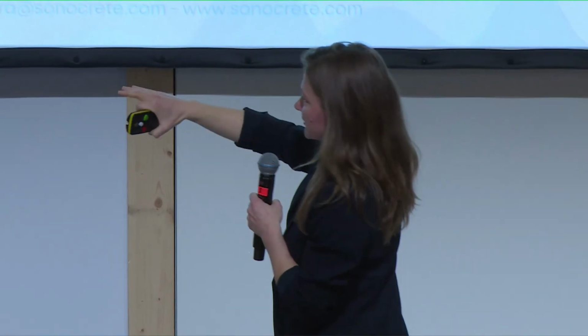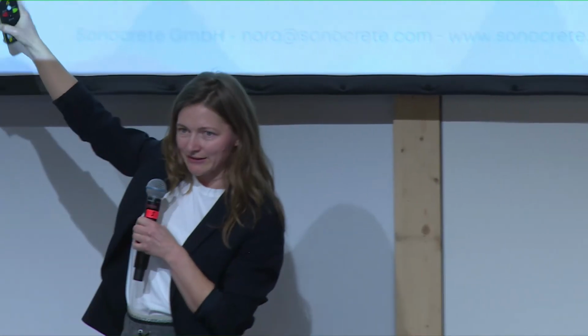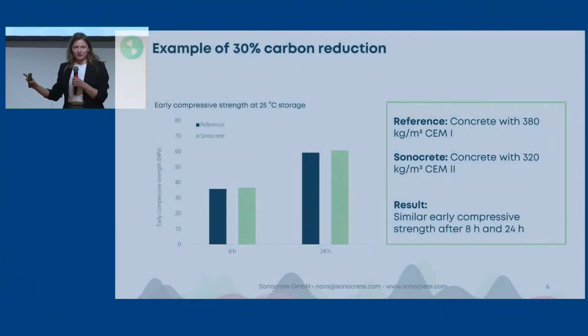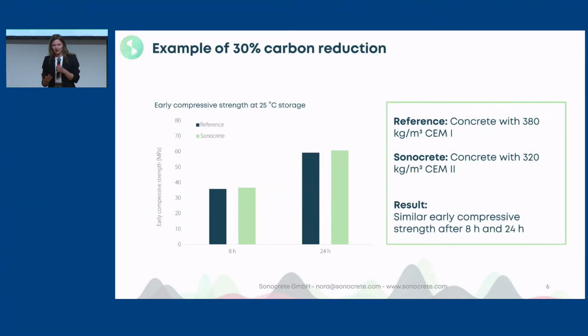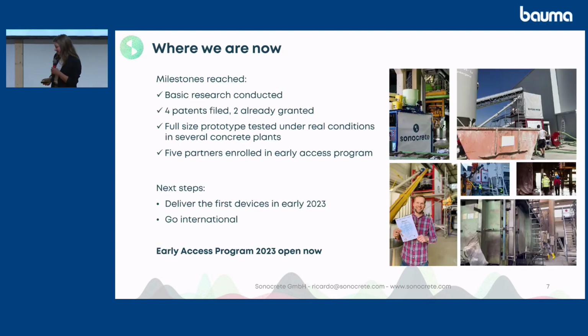Now we're looking at the left side. What we see is that both of these samples were ready. They had the same early compressive strength, which is what you need to strip a mold after 8 hours. The 8 hours was the relevant time for this partner. This was the time when they wanted to open their molds and take out the product, and it was ready after 8 hours. So 30% less carbon, but the same time for stripping. That's a big success, and it's one of our partners now, so we will be delivering a plant.